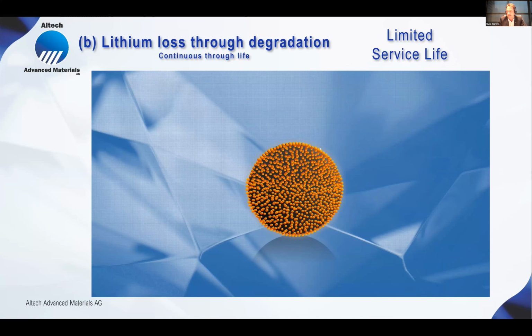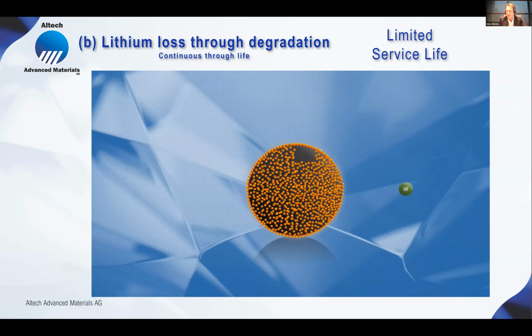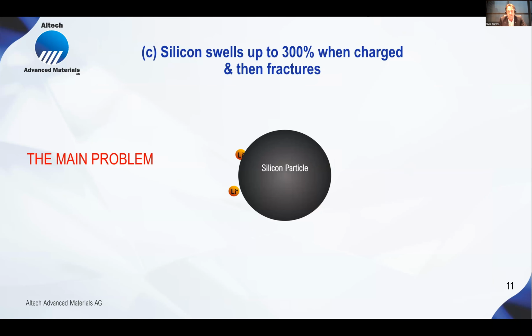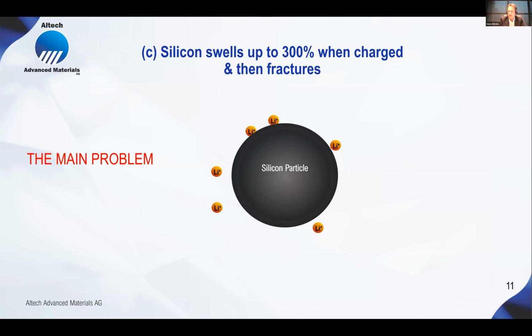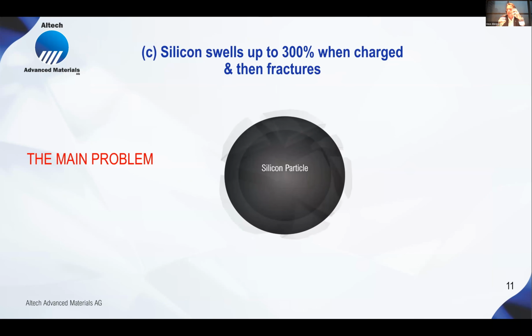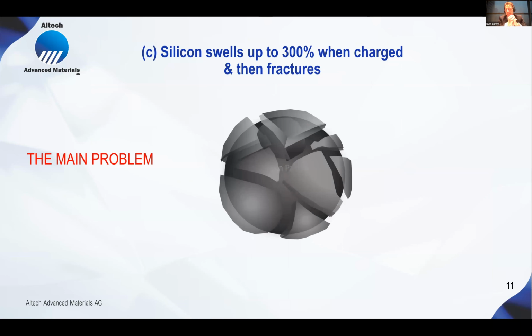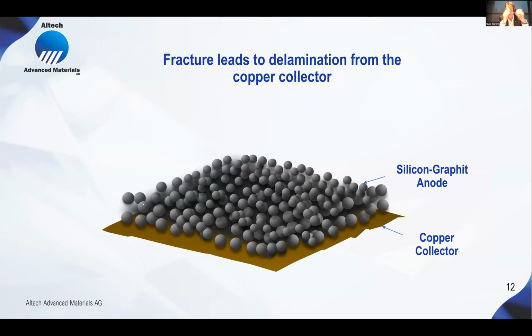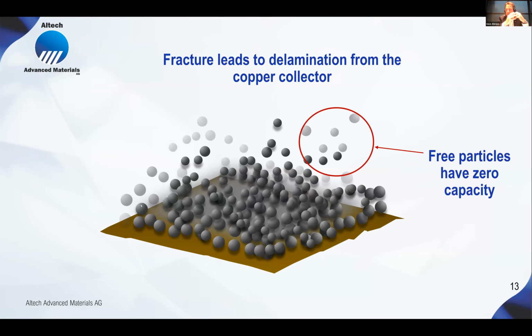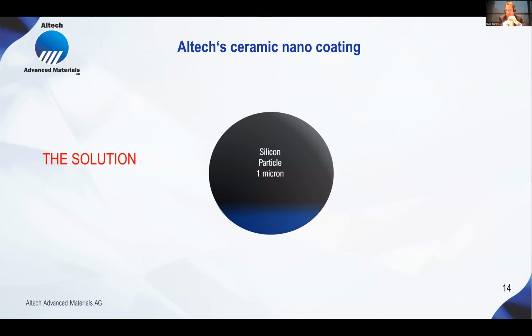That's totally counterproductive. Plus, the degradation goes on. This is hydrofluoric acid, other things. This layer is constantly destroyed, and therewith you lose your capacity. For example, on your handphone, you all experience it. But with silicon, there's one bigger problem. When the silicon collects, because of its high surface area, the lithium ions, it expands 3 times and they rupture. And when they rupture, they delaminate from the copper. And then the energy is lost and the battery is broken.